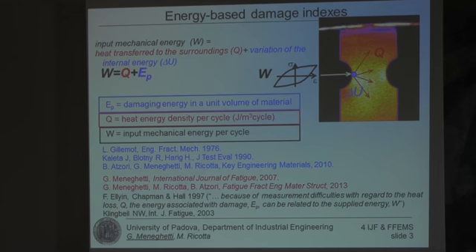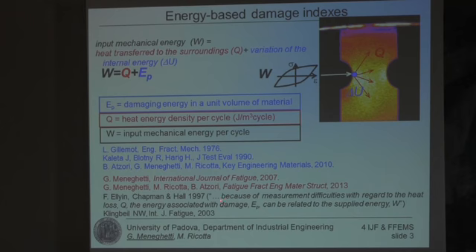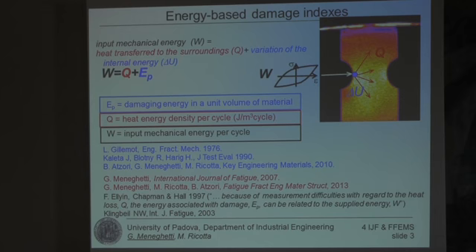And then the input mechanical energy, which is the area of the stress-strain hysteresis loop, has been used for example by Ellin in his well-known book, where it is interesting, in my opinion, to note that 20 years ago he stated that because of measurement difficulties with regard to heat loss, Q, the energy associated with damage, EP, can be related to the supplied mechanical energy, W. And he used the mechanical energy as a fatigue damage indicator. But now we can measure the specific heat loss in a quite simple way with a non-contact measurement system, like, for example, an infrared camera.